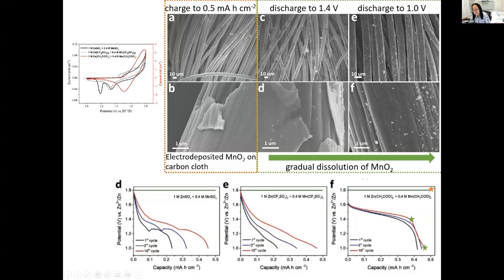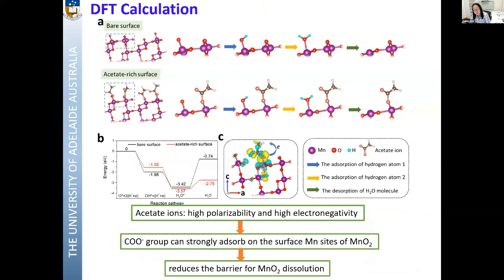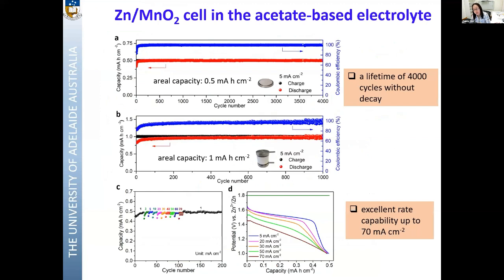From the discharge curve, we can also see the difference. In the sulfate and the sulfonate, we can see there are 2 plateaus corresponding to zinc and proton intercalation, right? But in the acetate-based electrolyte, we can only observe 1 plateau. And the voltage is higher compared to the other 2 electrolytes, indicating the reaction mechanism is different. And from DFT calculation, we found the acetate group can strongly adsorb on the surface of manganese oxide. So it can reduce the barrier for manganese dissolution, unlocking this manganese 4+ to manganese 2+ reaction, which makes the dissolution deposition reaction possible.